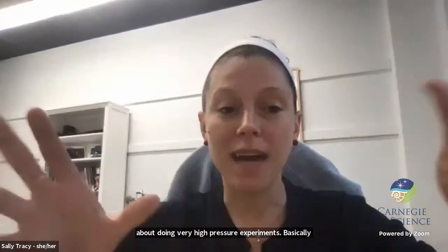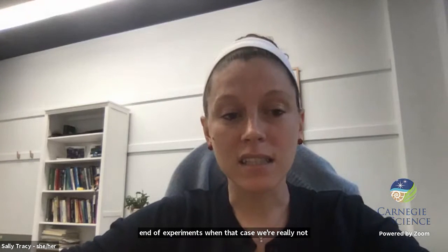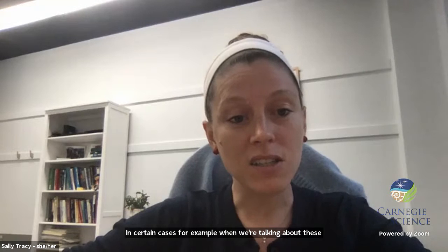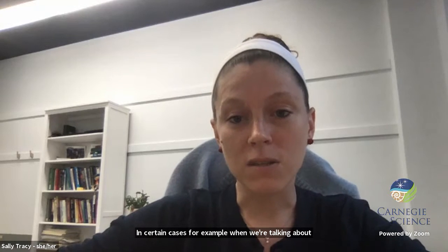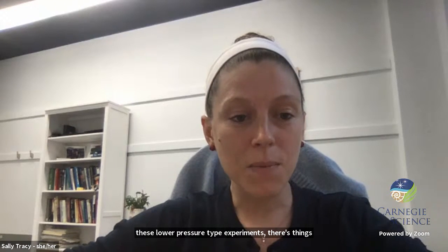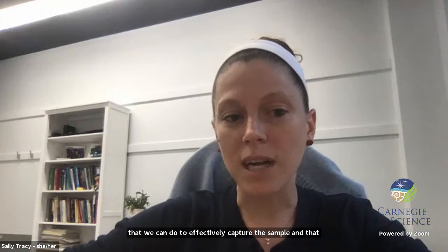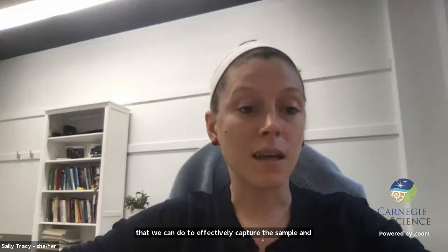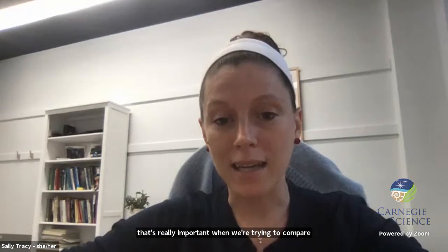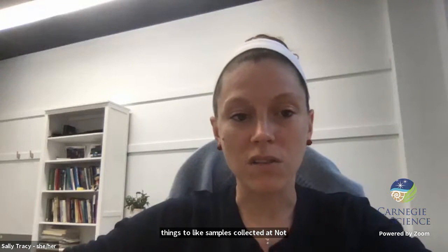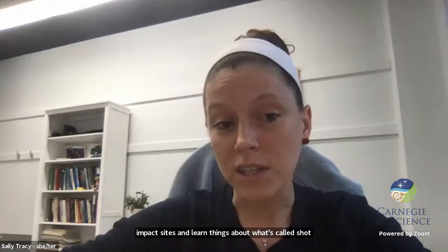So in that case, we're really not collecting anything. In certain cases, for example, when we're talking about these lower pressure experiments, there are things that we can do to effectively capture the sample. And that's really important when we're trying to compare things to samples collected at natural impact sites and learn things about what's called shock metamorphism in minerals, for example.